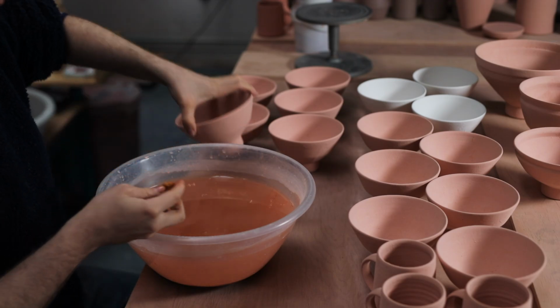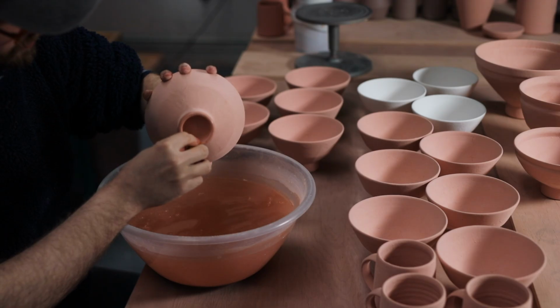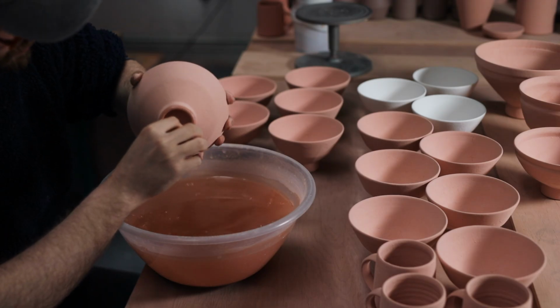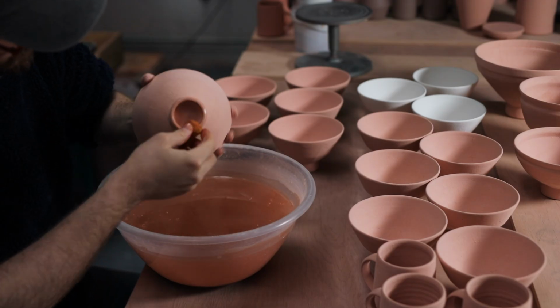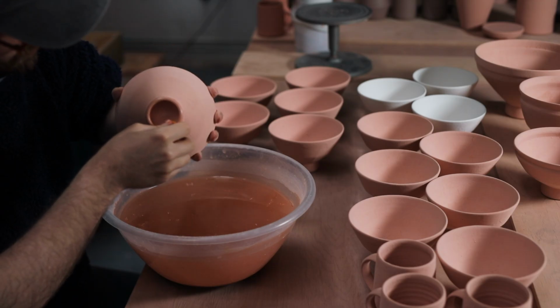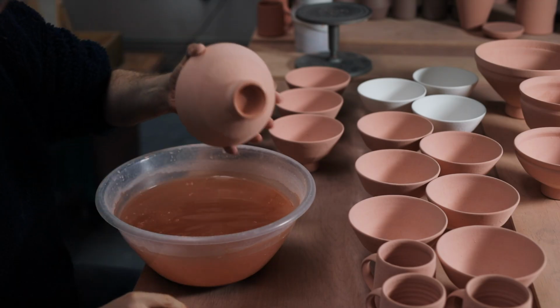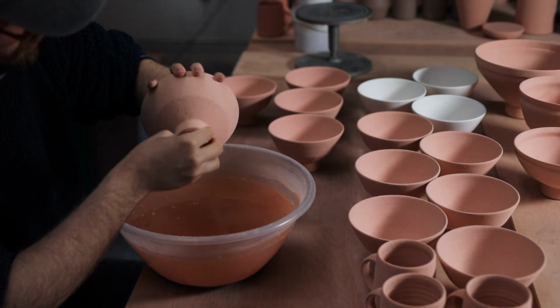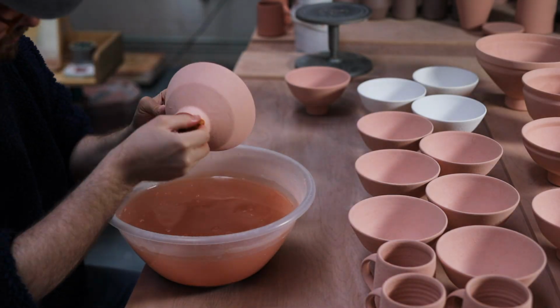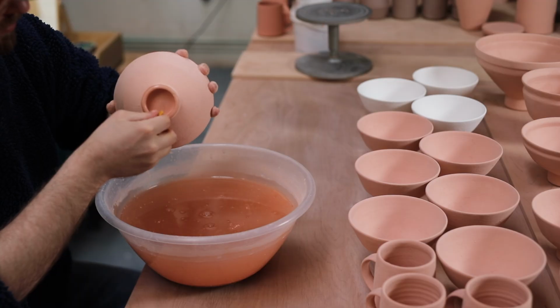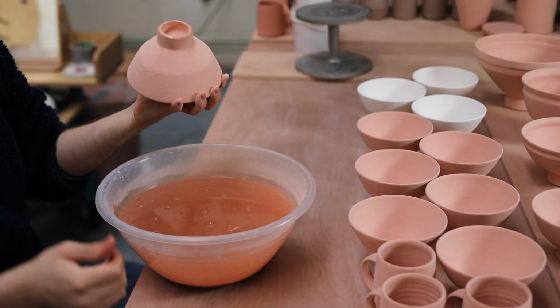It is often quite slow and arduous work, painful too, especially for my left hand that's actually holding the pot, as I need to grip them in such a way that I don't rub the surface, as the layer of glaze that coats them is really delicate and powdery and is chipped and damaged easily. I'm never just holding the pot without thinking. In fact, the way I handle the pot with my left hand is arguably the most difficult part of this process,